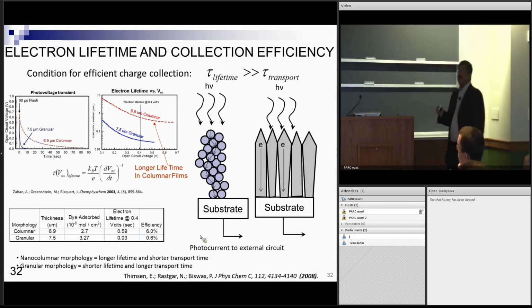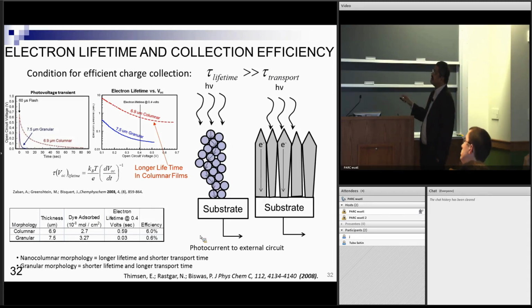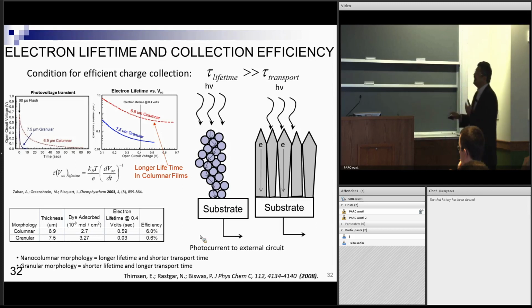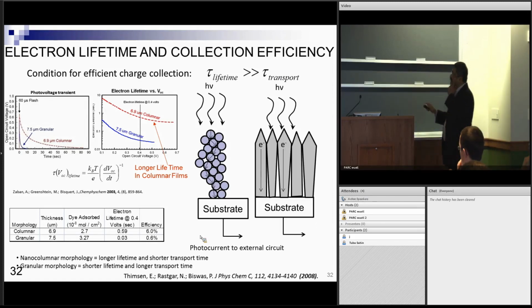I can go and do some lifetime measurements, as I indicated, by just tracking the open circuit voltage as a function of time, and you can see that the electron lifetime in a columnar film is much greater than that in a granular structured film. Okay, so that then of course just gives me additional support for what we have measured in a bulk way, and we can then fine tune these morphologies and so forth to be the most effective.